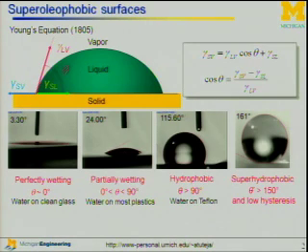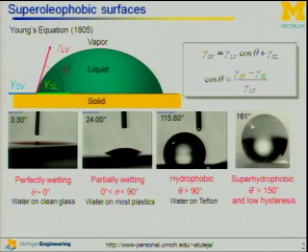The third is hydrophobic, where Young's contact angle is greater than 90, such as water on Teflon. And lastly, superhydrophobic, where theta is greater than 150 degrees and low contact angle hysteresis, which is the difference between the advancing and receding contact angles.